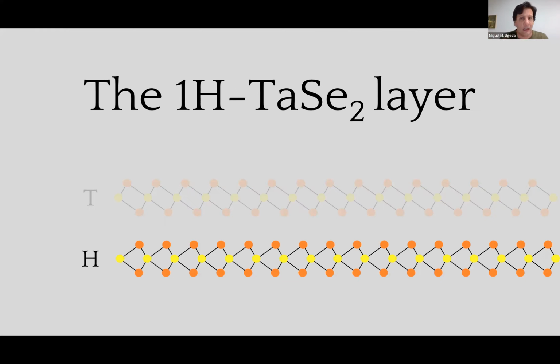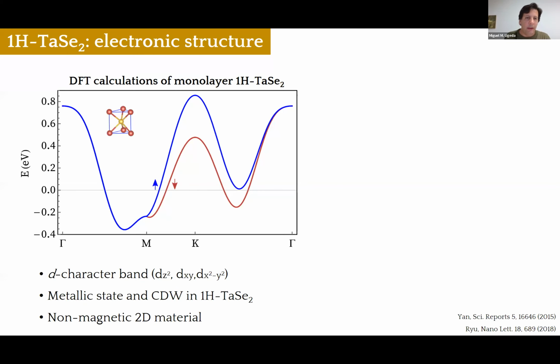Let me give you some words about the 1H system, the 1H tantalum diselenide layer. Okay, so the electronic structure of the 1H tantalum diselenide phase is dominated by only one single band that crosses the Fermi level and provides the metallic character to this material. As I said, this band has a D character coming from the tantalum atoms. And the only peculiarity about this band is the fact that it's spin split around the K point due to the strong spin orbit coupling. It's a non-magnetic material. We have done some experiments that I will not show today to prove that this material is not magnetic down to 2 Kelvin.